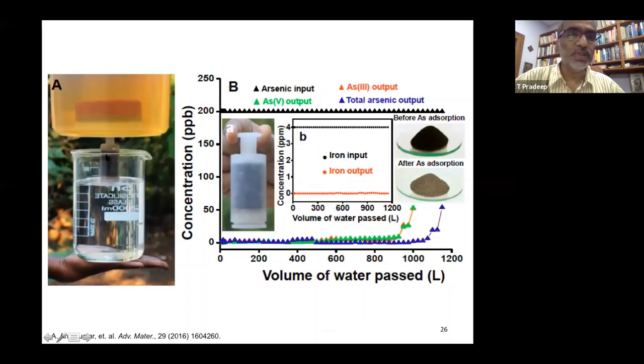So take about 20 to 30 grams of this material. And you take iron and arsenic containing water, both arsenic 3 plus and arsenic 5 plus. Iron is added because in most of these regions, iron is present, and also it gives you a color contrast. Arsenic is colorless and iron is colored. And this is 200 parts per billion of arsenic 3 plus and 5 plus combined, 100 and 100. And then you pass it through this, and this is what happens. And there is no arsenic.